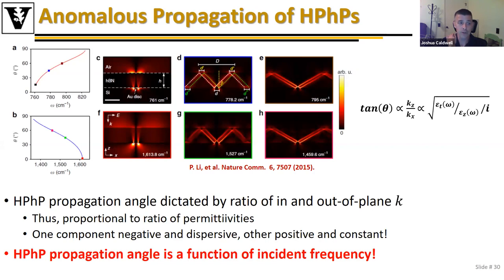So if I'm near the TO phonon in the lower Reststrahlen band or the LO phonon in the upper Reststrahlen band, if I launch a hyperbolic phonon polariton through some scattering element and it propagates through a slab of boron nitride, it'll propagate directly up to the top surface with something close to 0 degree transition. However, if I shift somewhere inside this band, you see that it will propagate at a fixed angle that's dictated by that dielectric function and the frequency of operation.